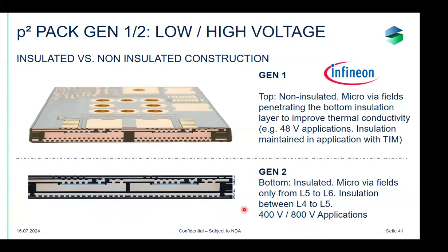For high voltage applications like 400 and 800 volt, it is not so easy anymore. And therefore, we are working on generation 2 right now in the series development. In that case, we're just leaving out one of these layers of copper-filled microvias, because the materials we are working with are very good insulators, but we are also working with materials with an increased thermal conductivity. Because if you just insulate here, then you're not only electrically insulating, but you're also thermally insulating. And this is a drawback. But as a system, you can achieve the lowest possible thermal resistances.